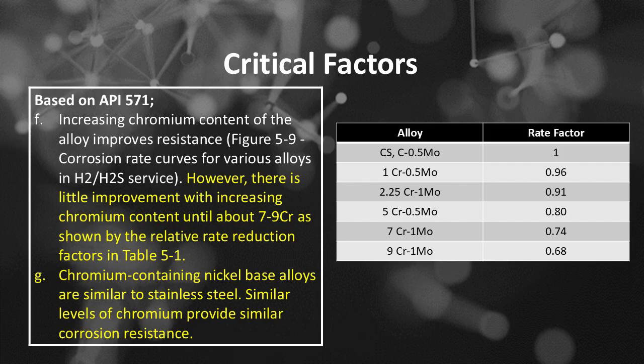Significant improvement starts around 7% of chromium, or rate factor 0.74, and continues at 9% of chromium, or rate factor 0.68. This means adding small amounts of chromium doesn't help much in hydrogen or H2 and hydrogen sulfide or H₂S service. You need at least 7 to 9% of chromium for meaningful resistance. That's why alloys like 7 chromium-1 molybdenum and 9 chromium-1 molybdenum are commonly used in high-temperature sulfidation environments. Molybdenum also helps, but chromium is the key driver for sulfidation resistance.